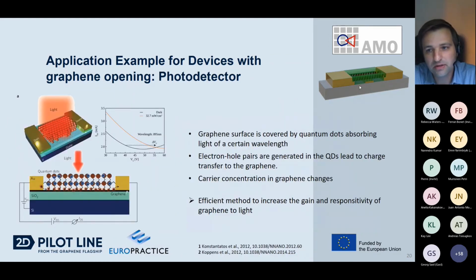Another application for having these devices with an opening on top of the graphene is shown here for a photodetector, where you can now functionalize the surface with graphene quantum dots. And these quantum dots generate electron hole pairs which are charged and then lead to a charge transfer into the graphene. And by this, you can detect the light by measuring a different resistance in the dark or in the illumination state. So this is also a method to increase the gain and the responsivity of graphene to light.